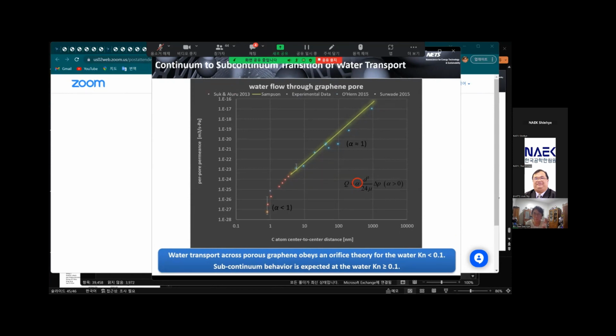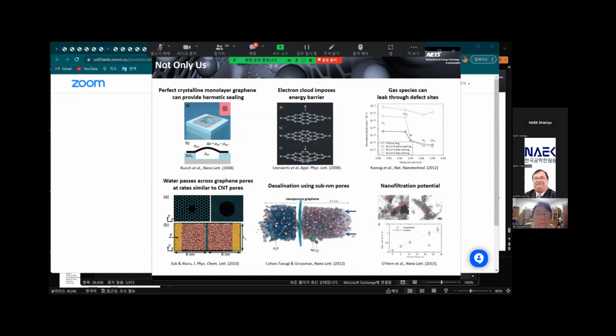A race has just begun to verify that prediction, with ambiguous experimental data for now, showing a large error bar and a pro-Sampsonian result. Transport at such small single-digit nanometer wide pores is not well understood theoretically, which is identified as an additional knowledge gap. The research field of transport across 2D orifice pores is at its adolescence. The field is gradually growing in engineering science, calling for scientists' further attention.